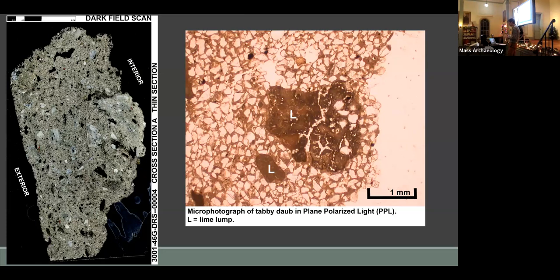Oyster shell is primarily composed of calcium carbonate, and when subjected to intense heat, carbon dioxide is driven off, leaving behind calcium oxide or quicklime. To effectively reduce oyster shells into quicklime, a temperature of 900 to 1,000 degrees Celsius has to be sustained. To underburn basically results in underburned fragments. It doesn't make for a good mix. To overburn lime basically results in dead burnt lime. That also is not good for these two structural issues. And lime burning also requires a lot of shell and a lot of fuel.